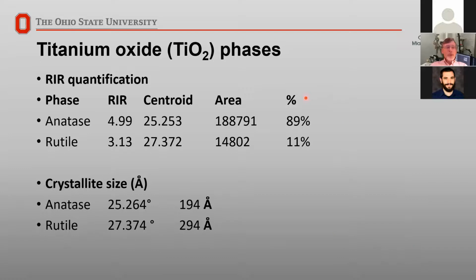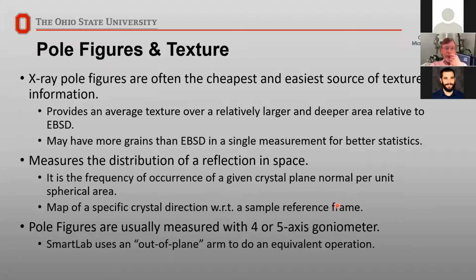So not only are we able to determine the type of crystals we have and the amount and their size, the other thing we're interested in can be the orientation or the distribution of the orientations of those crystals. Now in powder X-ray diffraction, we really like to have an infinite number of randomly distributed crystals without any kind of a preferred orientation. But in many materials, as you start machining them or rolling them, particularly in metals, they will often take a preferred orientation. All those little crystals will align in the same direction. So you can think of squeezing pasta dough through a die. All those pasta strands are going to line up in the same direction. So you can think of that in a way like fibers.